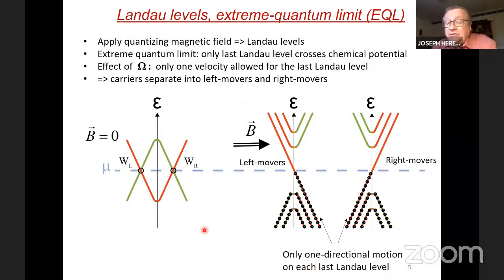Now, almost all the data that I will talk about are taken in the extreme quantum limit. So here are our two overlapping bands in the conventional Weyl semimetal. We actually never get there. And then the applied magnetic field opens the Landau levels in this system. The last Landau level is chiral. Because of the chirality, the last Landau level in one of the Weyl points has only one slope in velocity. So these electrons here can only move to the right. And this has the opposite slope, so the electrons here can only move to the left.